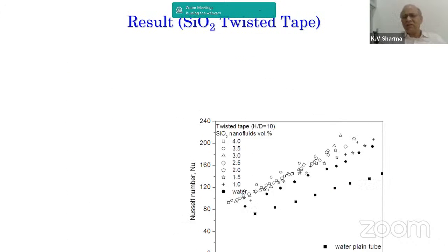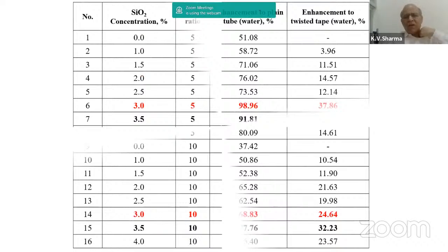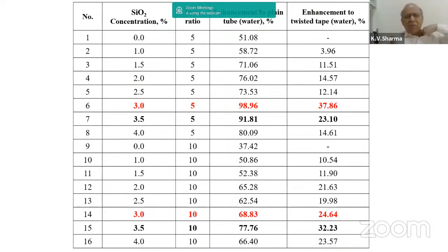For SiO2, once again, similar analysis. Taking the data and putting it in a tabular form, you see that for 3% concentration for SiO2, for H by D of 5, you get a maximum enhancement of 98.96%. When the H by D ratio has increased from 5 to 10, it has decreased.